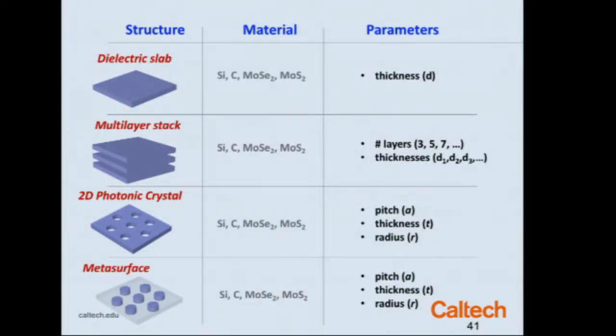So these are the structures that we're going to look at. We're going to look at dielectric slabs, just a uniform thickness, homogeneous dielectric slab, just a sheet of material. A multi-layer stack. So imagine you had high index sheets with low index sheets of a material like aerogel between them, and up to maybe 7 layers. So-called 2D photonic crystal. This is a motif that's familiar to optoelectronics people. We can make structures that exhibit guided modes and band gaps within the plane using a film that has a periodic array of holes. This gives rise to Bloch-like modes for light, periodic modes for light inside the film.